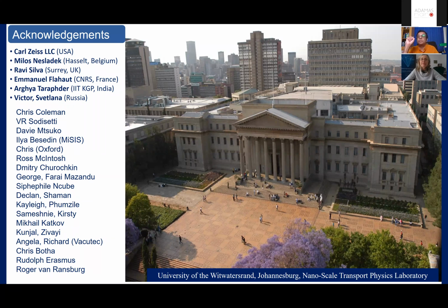These samples showed the superconducting transition, which is, I believe, from 0.8 Kelvin to nearly 3 Kelvin, 3 to 4 Kelvin. I don't remember exactly. I have deleted them. I didn't want to show the slides because it will take time, but we have measured 4 to 5 samples. Actually, we have measured many samples, but 4 different kinds of grain size. And this is the one which showed the best quality, something like 2.7 Kelvin at the superconducting transition temperature, which is very, very good.